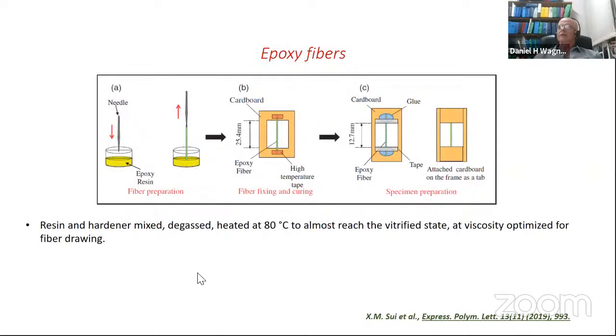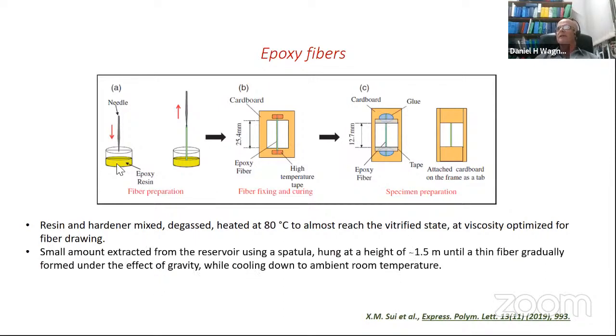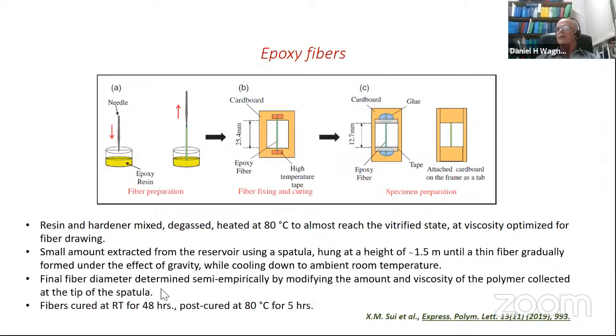So how do we do it? We mix the resin with the hardener, we degas, and we heat at 80 degrees in this case to almost reach the vitrified state, and the viscosity is optimized for fiber drawing. That's where you then extract a small amount from this reservoir here using a spatula or a needle, and you hang this at a height of about 1.5 meters in our case, until a thin fiber gradually forms. And this is just because of gravity, and it cools down to ambient room temperature very slowly. So this is what we do here, and then after that, once it's cured, you fix the fiber on a cardboard frame, which makes it ready for testing with a tensile testing machine. The final fiber diameter is determined empirically or semi-empirically by modifying the amount and the viscosity. You're playing around with those parameters at the tip of the spatula.